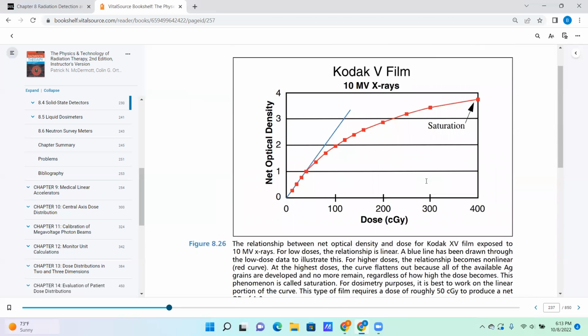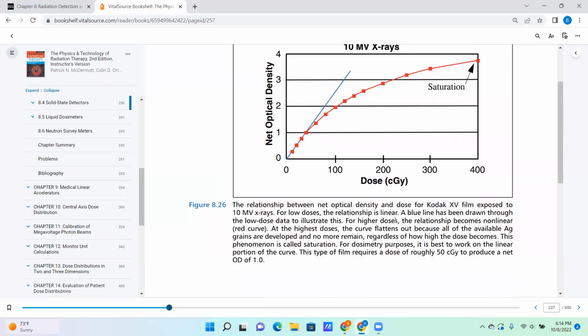It's right here. Here you can see the relationship between net optical density and dose for a Kodak XV film exposed to 10 MV x-rays. For low doses, the relationship is linear. A blue line has been drawn through that to illustrate that. For higher doses, the relationship becomes nonlinear, bending. At the highest doses, the curve flattens out because all of the available silver grains are developed and no more remain, regardless of how high the dose becomes. This is called saturation. For dosimetry purposes, it is best to work on the linear portion of the curve.